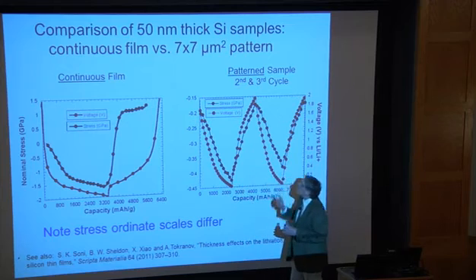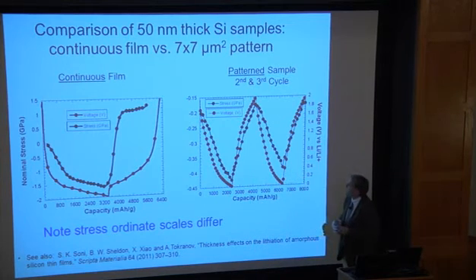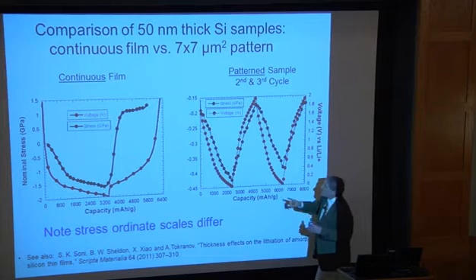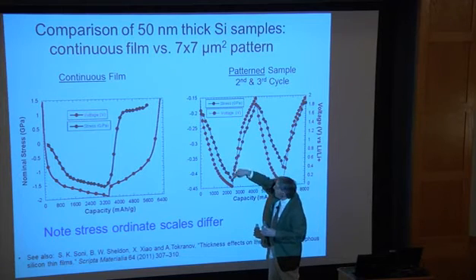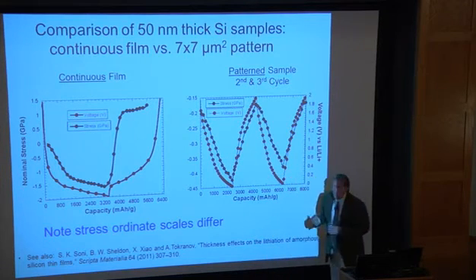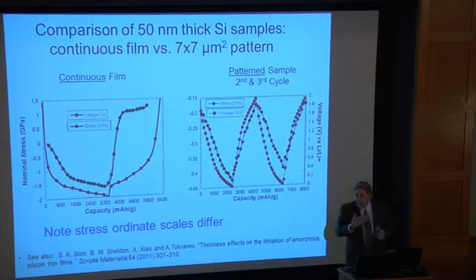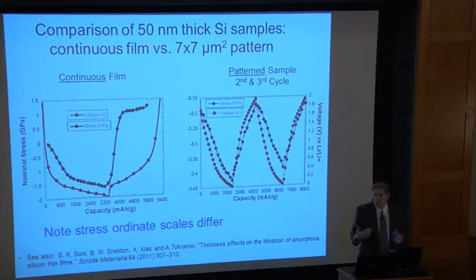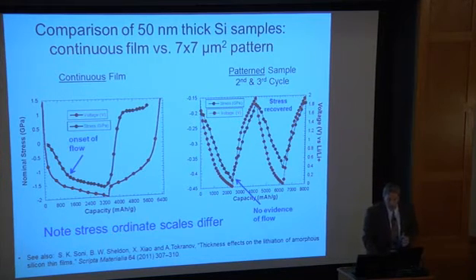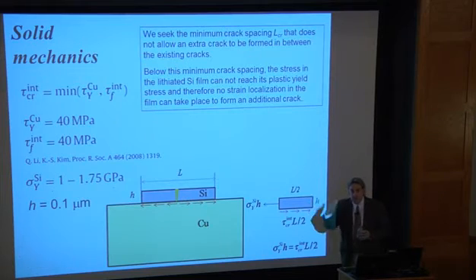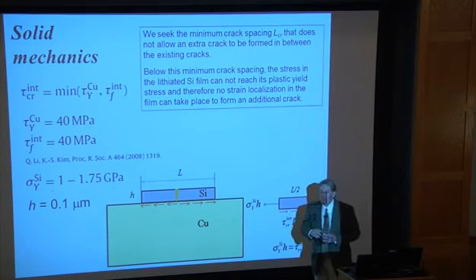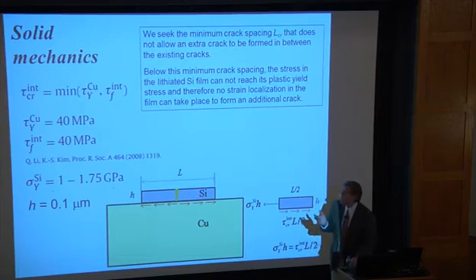If we instead go to the patterned electrode, and this is the 7 micron pattern, what we see is it's basically elastic. It comes down, it goes back up, it's very reproducible, and so you can infer from that that when things start to go into plastic deformation is when you start to run into problems as far as mechanical integrity. What happens is we find out you lose those electrode pads. They detach from the surface if you have too much degradation or too large of pads.